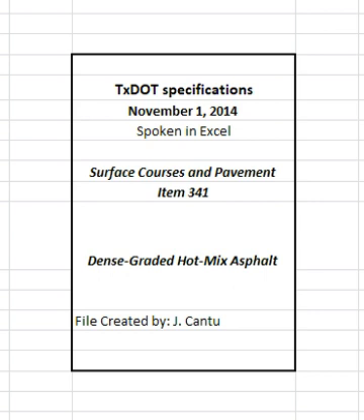Do not use department or contractor-owned RAP if the decantation value exceeds 5% and the plasticity index is greater than 8. Test the stockpiled RAP for decantation in accordance with Tex-406-A, Part I. Determine the plasticity index in accordance with Tex-106-E if the decantation value exceeds 5%. The decantation and plasticity index requirements do not apply to RAP samples with asphalt removed by extraction or ignition.